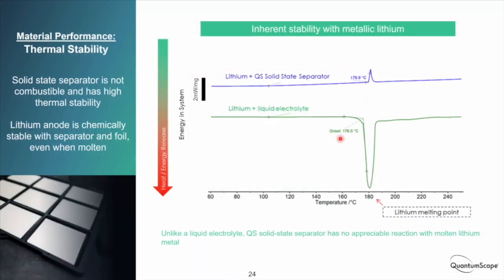One point on safety here, we wanted to show that our separator is stable against lithium. So what we did is we put lithium in contact with our separator inside a DSC device, a differential scanning calorimeter, basically a device that can measure heat flows in and out. So with lithium in contact with our separator, as we heat up, you see basically little heat flow in or out of the system. When you get to 180 degrees C, that's where lithium melts. So you see a little bit of an endotherm here. That's the latent heat of melting lithium. And then as you continue to heat molten lithium in contact with our separator, there's no exothermic reaction that we see.